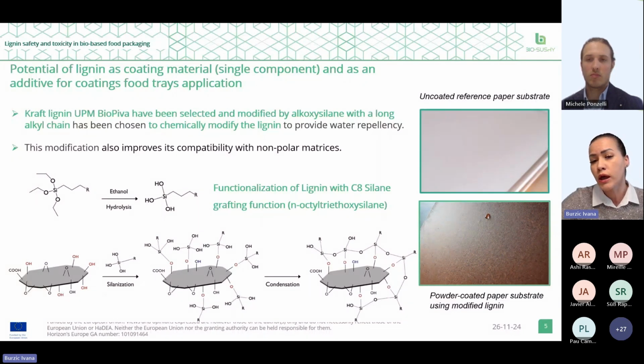Because due to its nature, lignin tendency is more to be polar than non-polar. Therefore, it has to be modified to provide certain water repellency. On the right-hand side, you can see two different examples of the modified and not modified lignin coated on a paper substrate. This is just a bit on the chemistry of lignin.